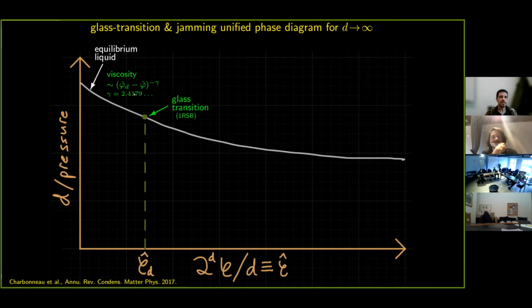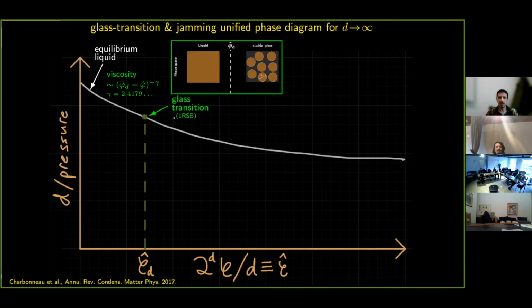indeed numerically, but nevertheless to the precision allowed by the numerics. What happens at this glass transition is a replica symmetry breaking transition. If you think about the phase space of the liquid, of course it's ergodic and it can go to all of the states. But once you cross this glass transition, the phase space is broken into regions that are not accessible dynamically, because the free energy barriers between any two of these basins are infinite in the thermodynamic limit. So you have a partition of configuration space into different basins that are not connected, but nevertheless, the calculation can still be extrapolated into this glassy state, which is the equilibrium, and it's not exactly equilibrium because it's not ergodic.